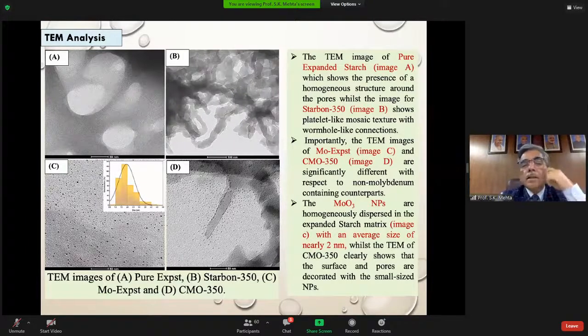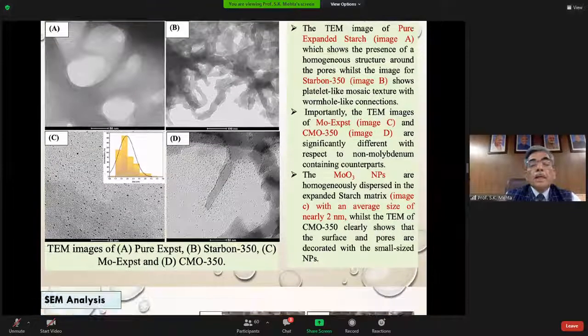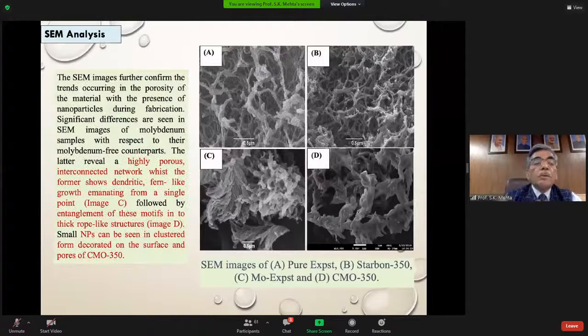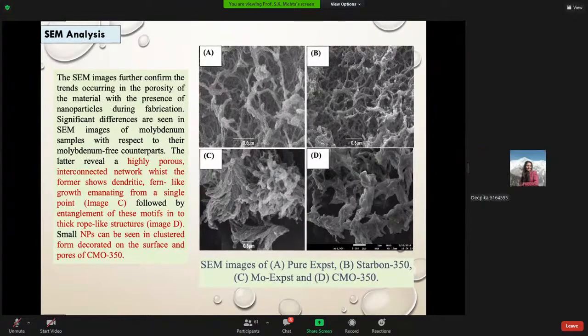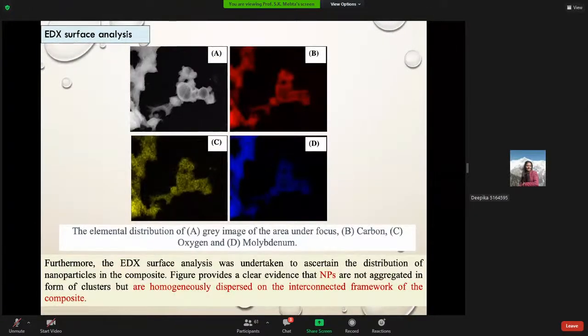In the TEM analysis you can see A is pure, B is starbon, C is molybdenum based, and the third is CMO based. So you can see these molybdenum nanoparticles on starbon are very well visible. Then they are very stable also, that is proved from our studies. Similarly, the pore size we have already seen, but their network structure can be seen very easily in these pictures. So EDX was done.